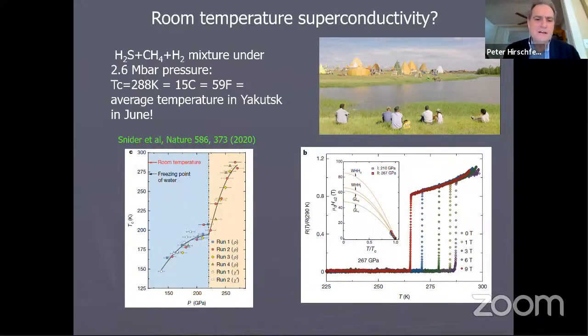Here are some of the data. This is TC as a function of pressure, and there is some kind of a transition at 240 and then 220 maybe, and then it goes up to 260 and it gets quite high. And these are the resistive transitions that were shown in the original paper. They are very sharp, if you notice. And normally we consider that good, but it's a little worrisome for some people.